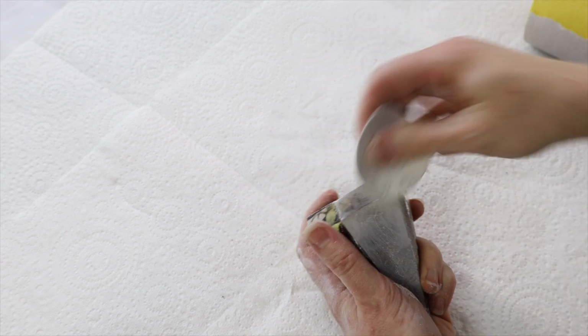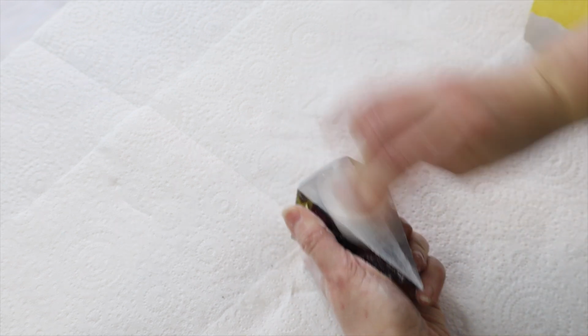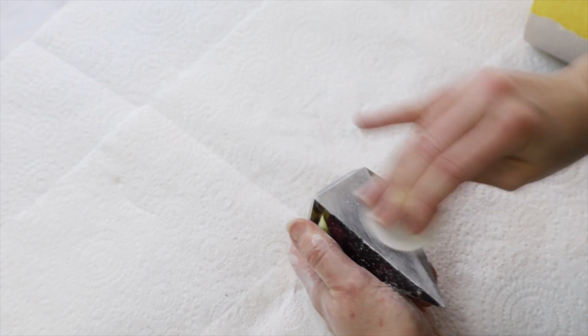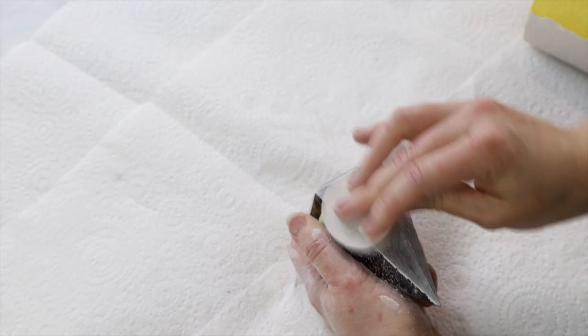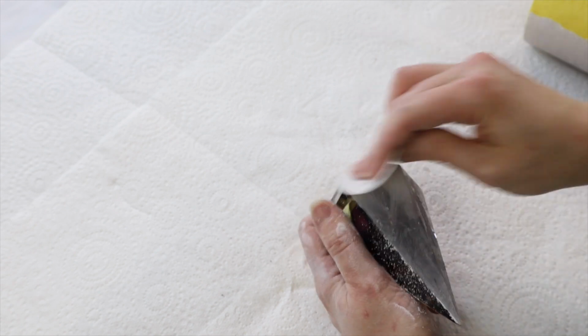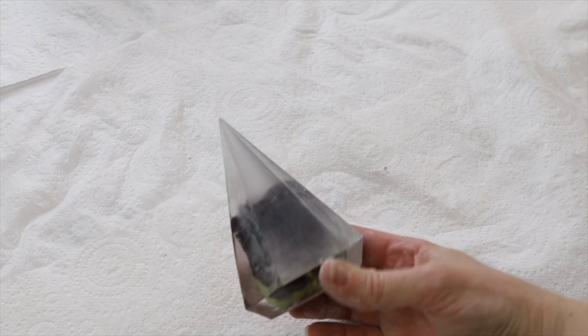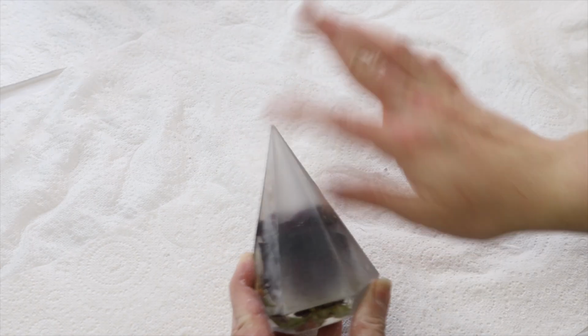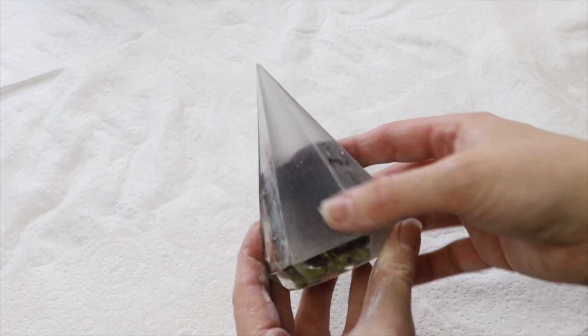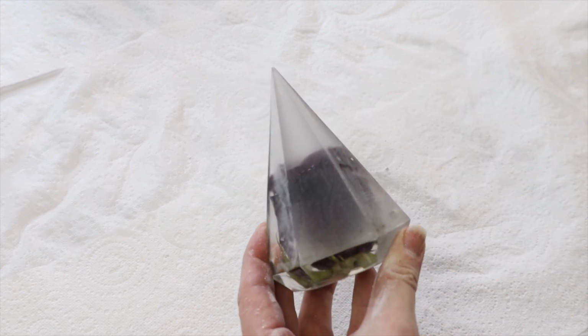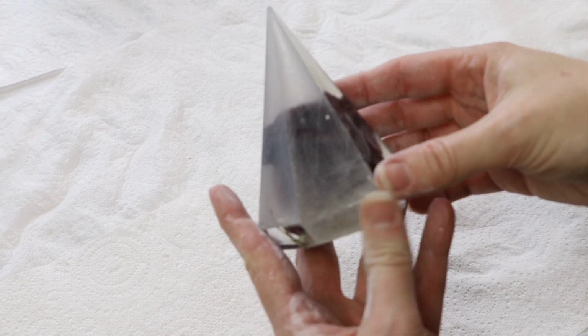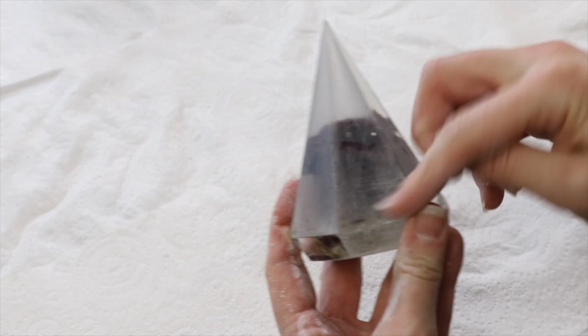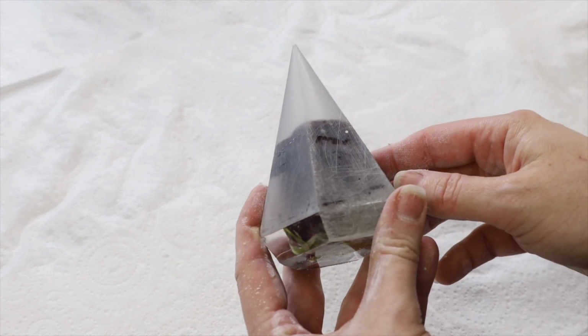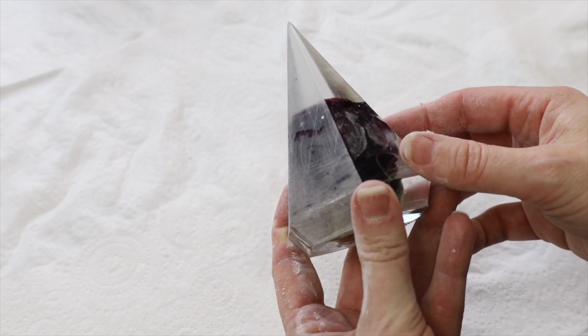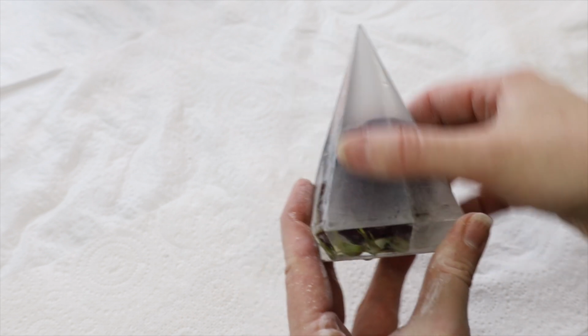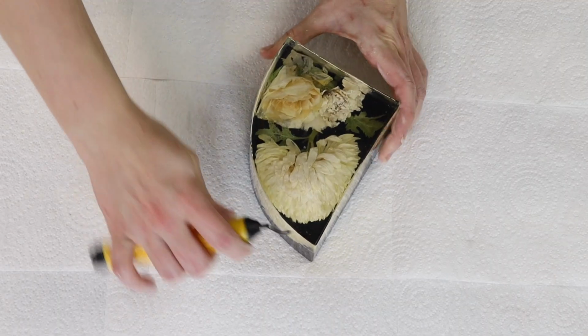Now, personally, I like to pick a 200 to 240, I find is the most ideal grit of sandpaper to use. It's rough enough that it will let the resin attach and adhere to the whole piece no matter what shape it is, but it's also not too rough where I'm going to be damaging my piece and end up with big sand marks going through my piece. Like you can see here where I did use an 80 grit to sand back this side, and now I do have quite big lines going through it, where the other side I used a 200 grit and I don't have any of that damage from the sandpaper.